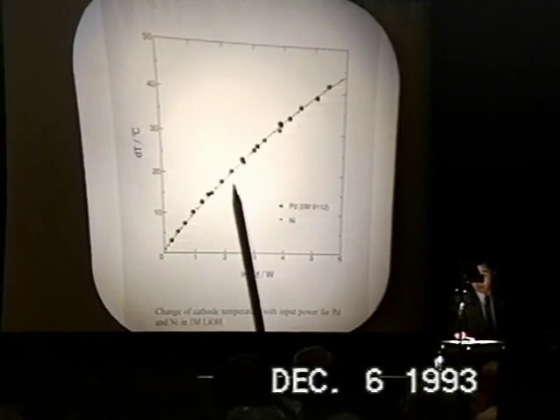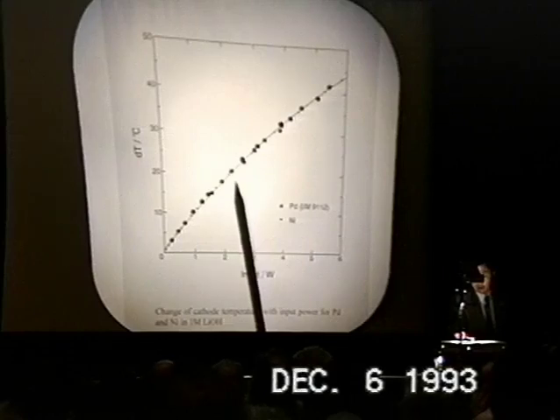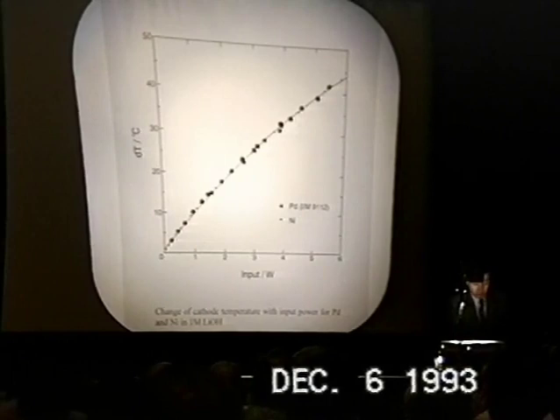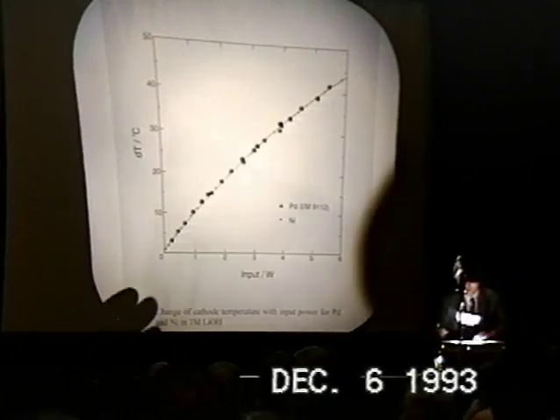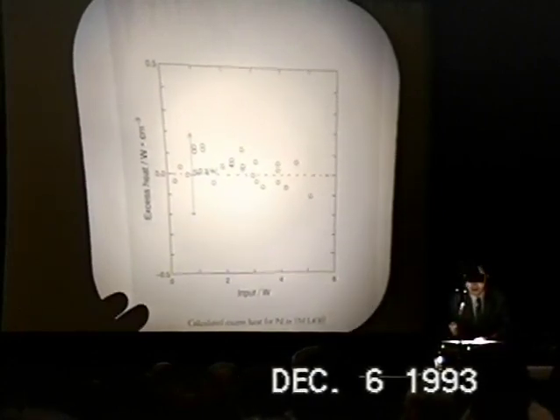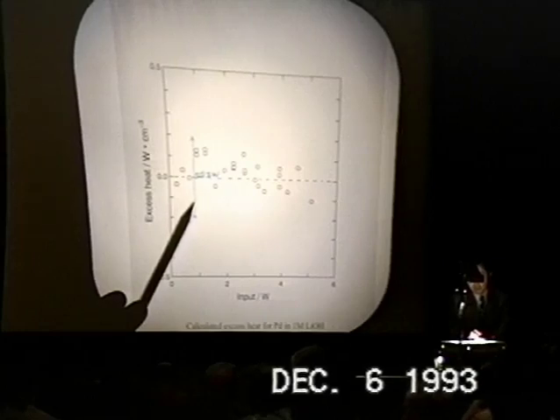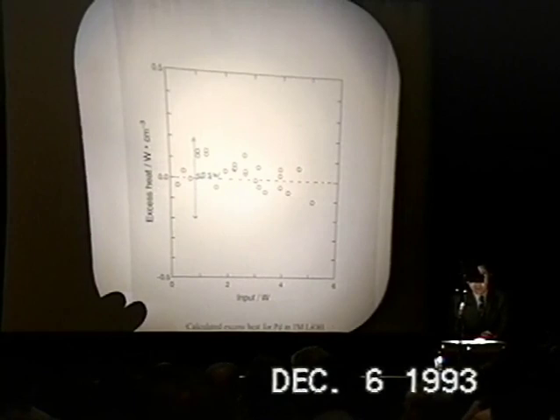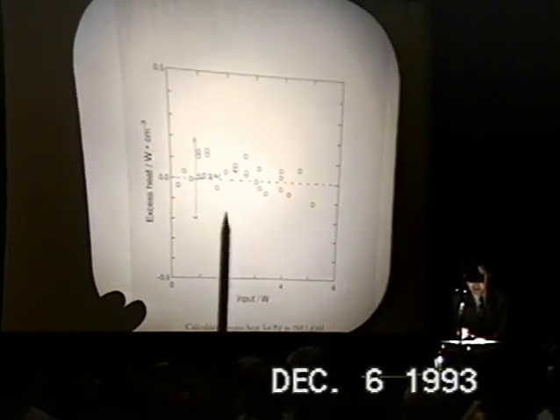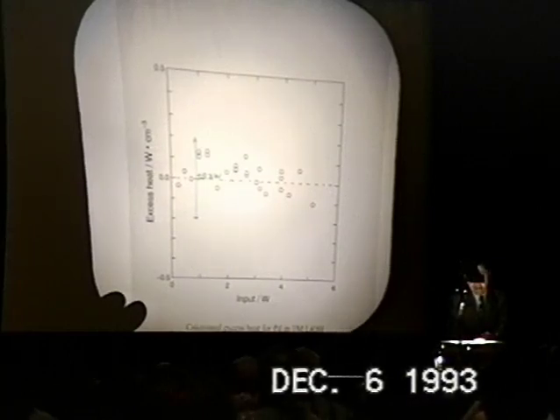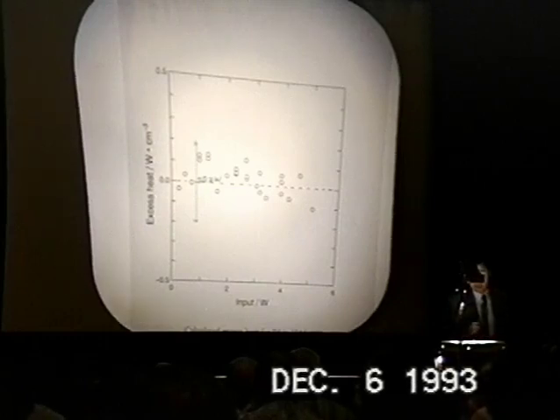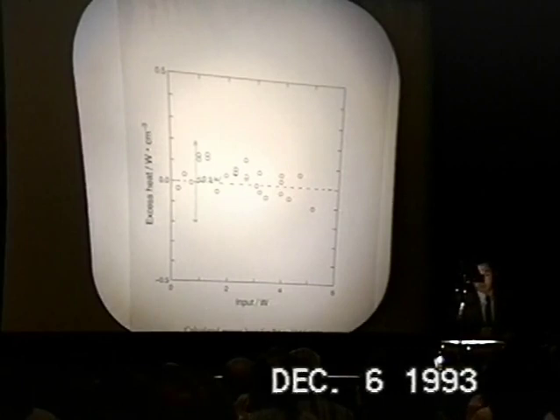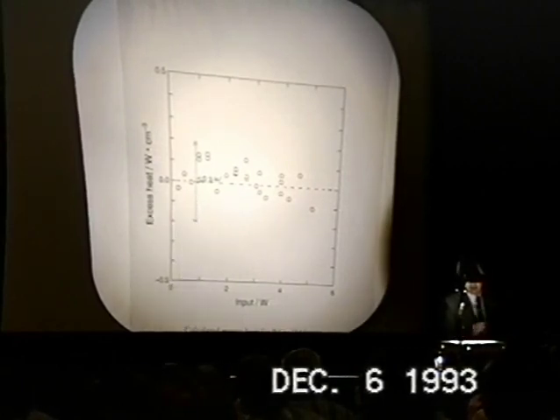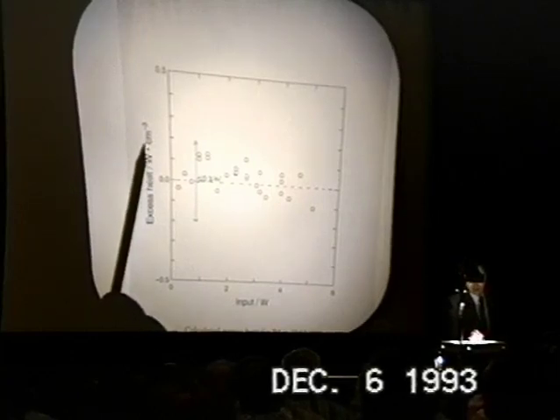So we see a very close correlation or coincidence between nickel data and palladium data. So from these data, we try to estimate the accuracy of our excess heat measurement, which is given here. So I'm plotting the data points scattered from the calibration curve. So these 5 points show the deviation of the data on the palladium electrode from the calibration curve, which is not so bad. In this case, I would say our accuracy for the excess heat measurement is probably plus minus 0.2 watts per cc of palladium cathode.